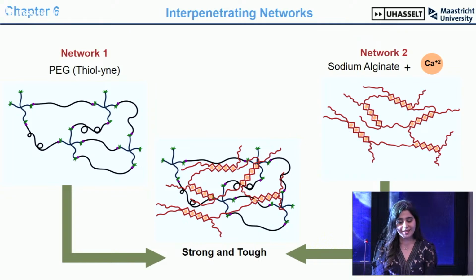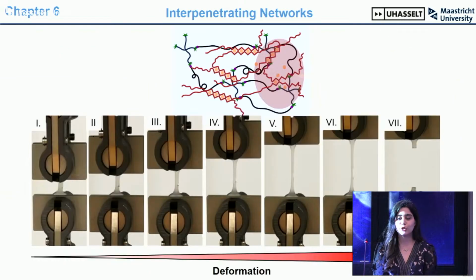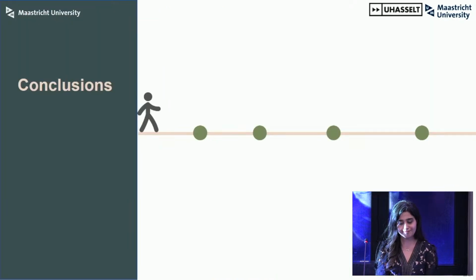This was done in Chapter 6, where an ionically cross-linked sodium alginate was added to the PEG network developed in Chapter 3. The reinforcing effect of adding alginate to the system depends on different factors, such as characteristics and concentration of alginate, the order of network formation, and building blocks forming the PEG network, which all are important to consider when designing hydrogels for different applications. But in general, alginate can dissipate energy by unzipping under stress. This creates a larger deformation zone around the crack tip, reduces the amount of the elastic energy transferred to the crack tip, and slows down crack growth.